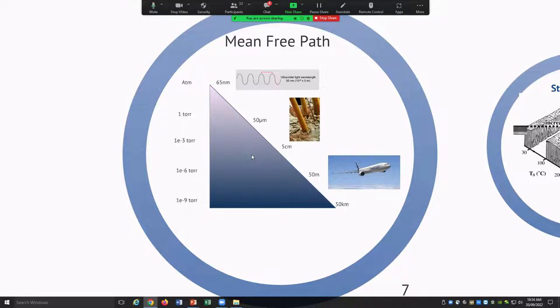As we reduce the pressure, we reduce the number of particles in the chamber, and the distance they travel before they hit gets longer and longer. So up in outer space, you're talking sort of 50 kilometres before it hits another atom. They're the two extremes. Around rough vacuum, so 1 × 10⁻³ torr, we're talking, you know, centimetres. High vacuum, 1 × 10⁻⁶ torr, you're talking metres. And our depositions typically happen around 1 × 10⁻³ to 1 × 10⁻⁶ in this region. So you're talking distances of centimetres to metres before they hit something.